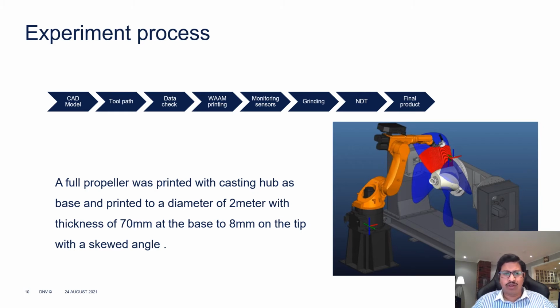So we took a CAD model, and then the toolpath design was established to check all the errors in the software used. Then the data check was completed, and it was sent to the WAAM 6-axis robotic arm machine. We had a lot of monitoring sensors to see the interpass temperature and the melt pool solidification, and by using optical pyrometry as well as optical cameras, we were monitoring the diffusion. Finally it was ground, it went through non-destructive testing, and the final product was done.